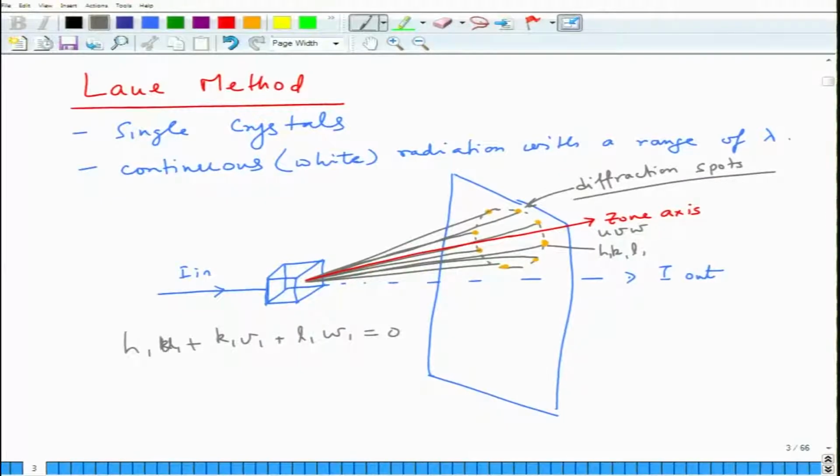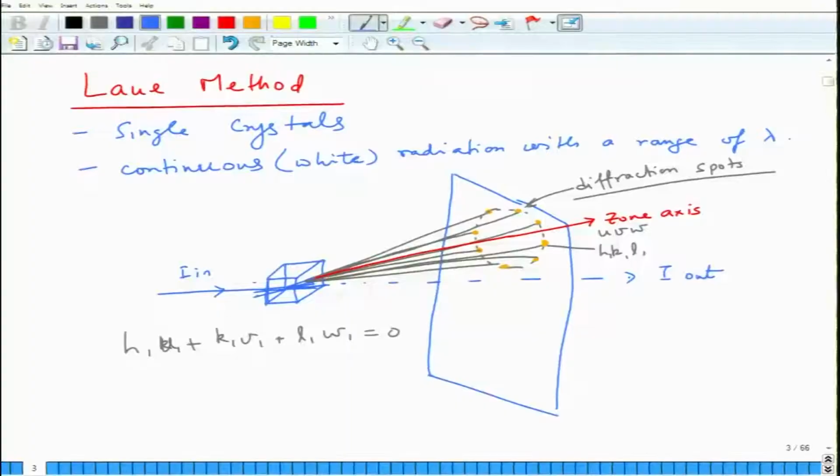So what basically it means is that you will have a zone, you will form a cone, and this is the transmitted beam, typically the angle. We know that for most of these, the plane orientation would be, if you combine these two lines, some plane would be like that, some plane would be like this. So planes will have different orientation, but not all planes, only those planes which have appropriate interplanar spacing and angle satisfying the Bragg's law. That is why we use variable lambda,